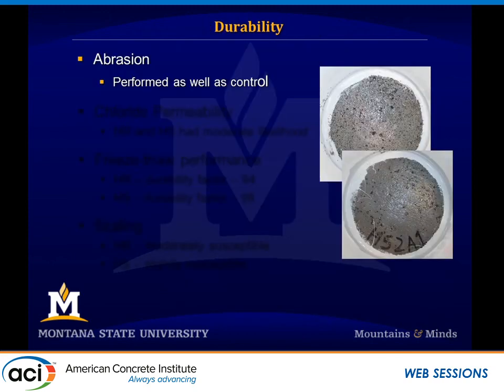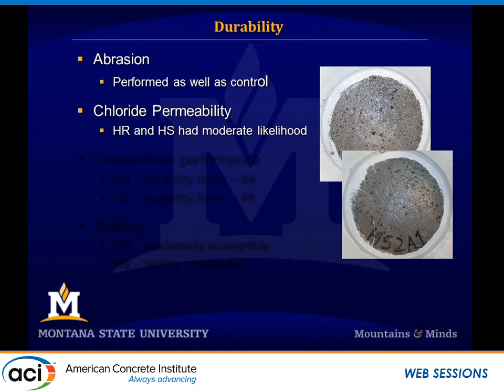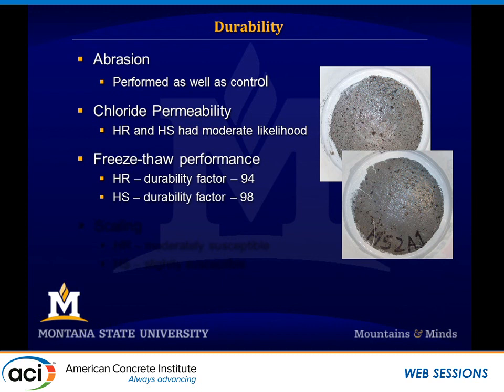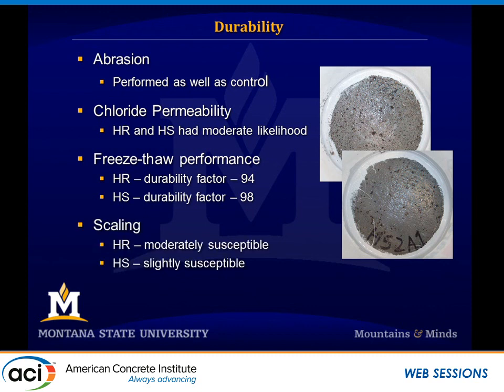In terms of the other durability properties, abrasion, it performed just as well as our control specimen. Chloride permeability, it had moderate likelihood. Freeze-thaw performance, it performed great with respect to freeze-thaw. The durability factor of 100 means it was perfect, so it was close to 100. And the scaling, moderately susceptible and slightly susceptible, so scaling was not determined to be an issue. And so in terms of durability, everything was fine.